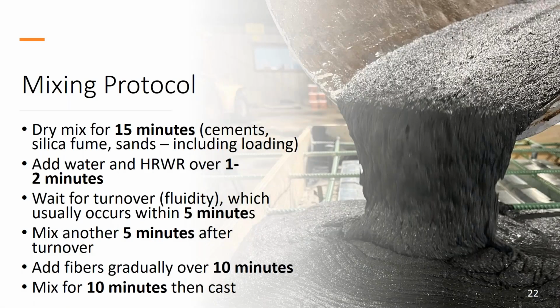So the mixing protocol is one of the things that I think a lot of people find to be difficult or think that this is not feasible to do, but it is very feasible. This is the mixing protocol that we used. We dry mix the material for 15 minutes. Typically, this is actually a function of the truck and where it's going and where it's coming from.